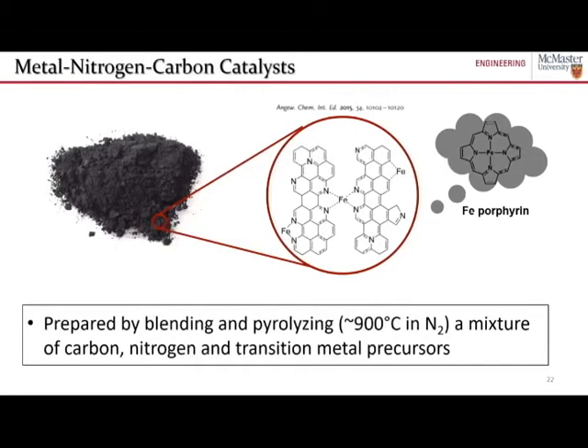Now, these materials are prepared by relatively straightforward processes, simply taking a transition metal salt, a precursor for carbon and a precursor for nitrogen, blending them all together and heat treating them in a tube furnace at something like 900 degrees Celsius in nitrogen can form these types of catalysts.